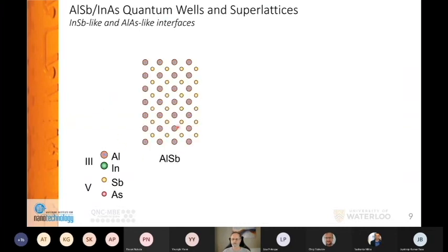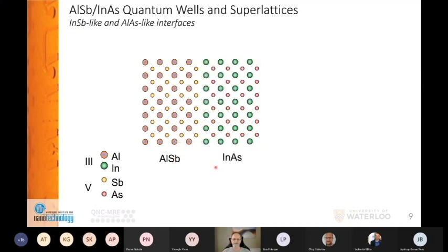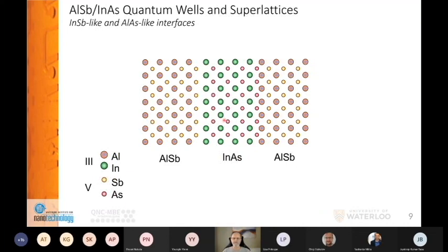And just an illustration of interesting interfaces in this material system. This is showing molecular beam epitaxial growth of aluminum antimonide. Then we grow indium arsenide. Everything seems to be nice and simple. But even if everything was that clean, the thing to notice is that even though the materials here are relatively lattice matched within 1%, the interfaces can be very strained. So there's no way to go around that.